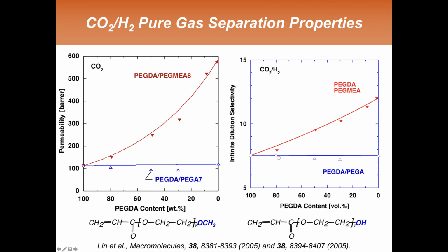However, when this more free and flexible side chain material is put into the polymerization, every time you put more of it in, permeability of carbon dioxide goes up, and in this case we can see it going up by a factor of more than 5. So we're getting strong interactions that favor CO2 transport, and a highly mobile matrix that favors high CO2 diffusion.